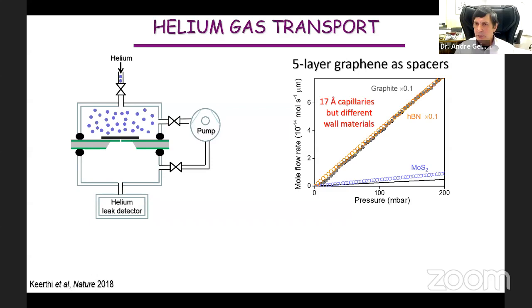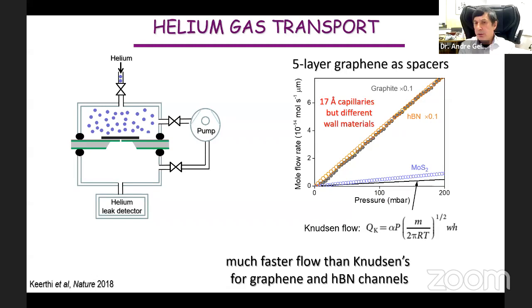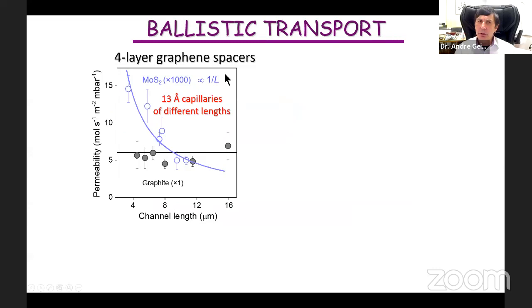Probably not a big surprise, okay, something different. But what is really surprising, if you compare with what you expect from classical physics, Knudsen flow, you find that molybdenum disulfide shows what you essentially expect from capillaries: classical Knudsen flow, where molecules go through the channel diffusively scattering. For graphite and boron nitride channels, you get a 100 times enhancement. You can also make the same capillaries of different lengths, from molybdenum disulfide and graphite, and with a huge difference, as you can expect, by a factor of 1,000.